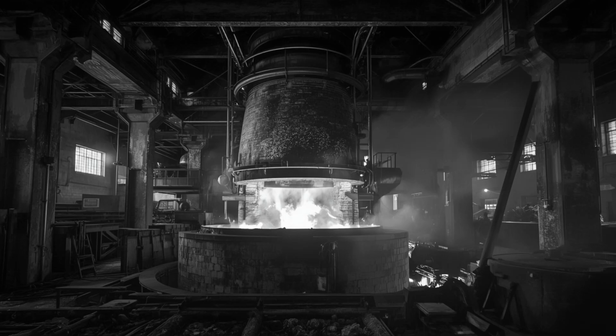Under sustained heat, particularly heat maintained for months without interruption, this bound water is slowly driven off. As it leaves, the crystal structure collapses slightly, the material densifies, and the brick shrinks. It's a small effect, perhaps 1 or 2% of total volume, but spread across thousands of bricks and sustained over months, it adds up. The brickwork is contracting from the inside out, each individual unit growing slightly smaller as it loses structural water under the relentless heat of the furnace.